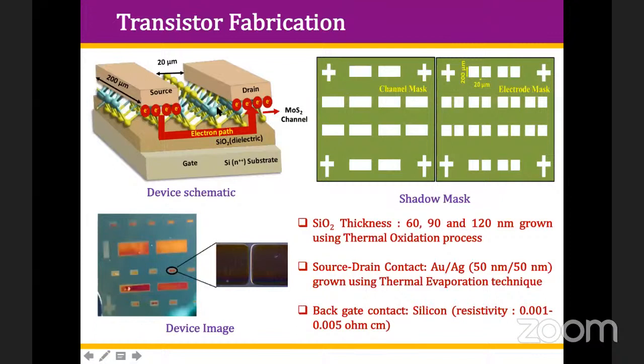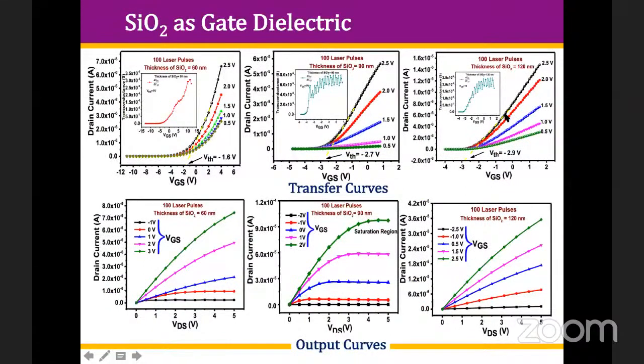And here we change the thickness of this channel: the monolayer, bilayer, tri-layer, and then source and drain. The separation between source and drain is just 20 micrometer. And these are the masks using which these transistors have been fabricated in the laboratory. And the thickness of the silicon dioxide dielectric, we first change from 60 nanometer to 90 nanometer and 120 nanometer. And then we study the output and transfer characteristics. So these are the transfer characteristics, and these are the output characteristics using silicon dioxide of 60 nanometer, 90 nanometer, and 120 nanometer. And well-defined transistor characteristics were obtained as in the case of an FET. Clear?